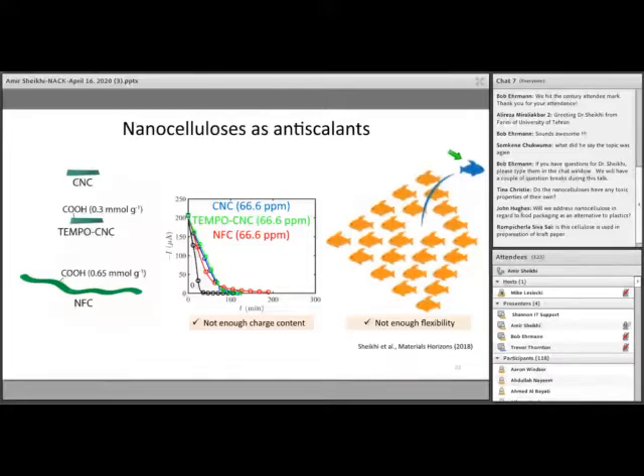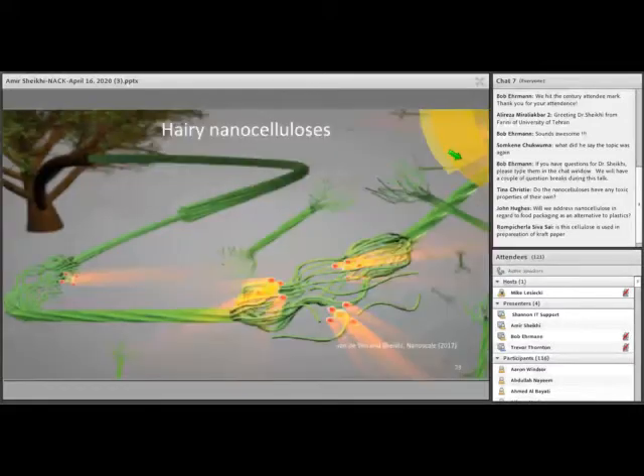So we thought, can we be this blue fish and swim against the flow and engineer cellulose in a way that it performs as an anti-scalant? And we took a look at the plant cell wall, and as I mentioned, it is made of crystalline regions, as you can see here, and amorphous regions. So what we did was to preferentially oxidize the amorphous regions using some chemicals that I will introduce in the next slides, and increase the solubility of the fiber from the amorphous region to break it down into cellulose nanocrystals that are sandwiched between 2 layers of highly functional amorphous chains. That's why we call them hairy nanocelluloses.